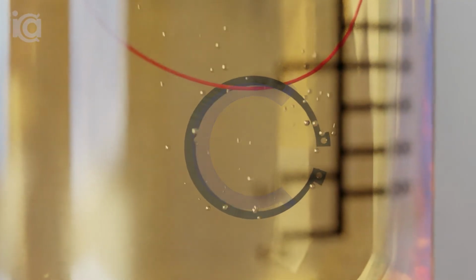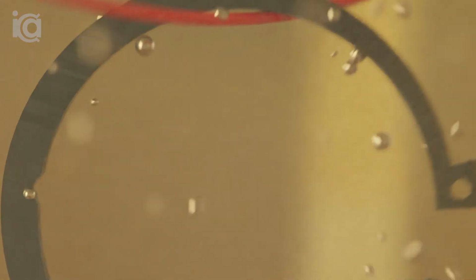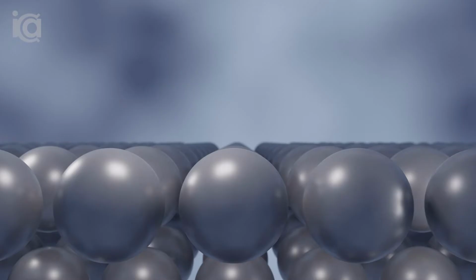During the pre-treatment stage, the danger of hydrogen embrittlement is highest during the pickling process. In pickling processes, metal and metal oxides are dissolved in an acidic oxidation accompanied by a reduction in which hydrogen formation can be observed. The surface phase reaction of hydrogen formation can be understood from the Tafel, Volmer and Heyrovsky reaction.